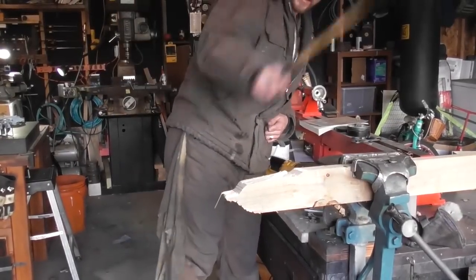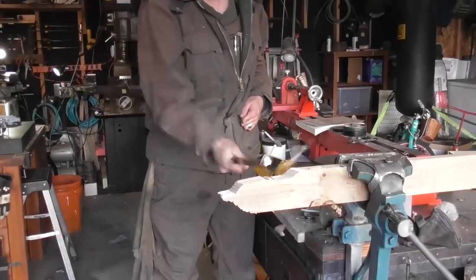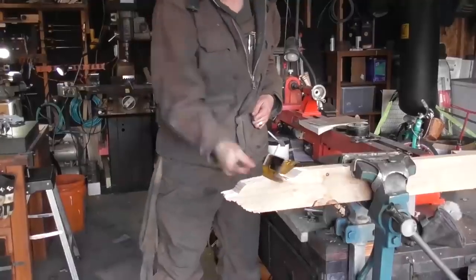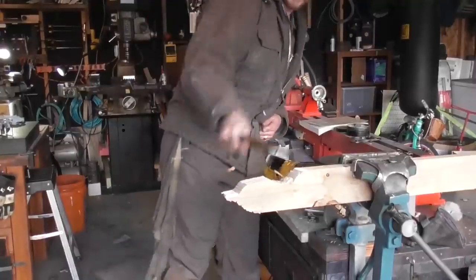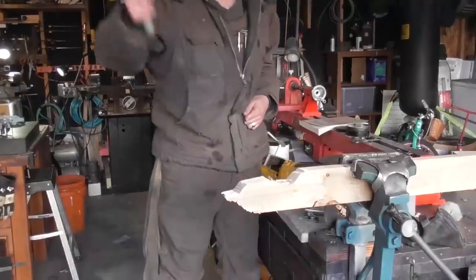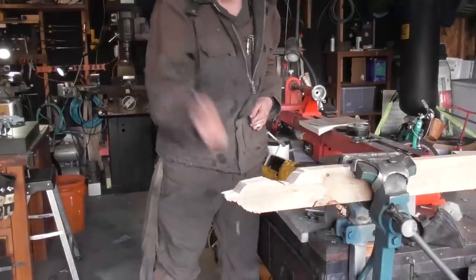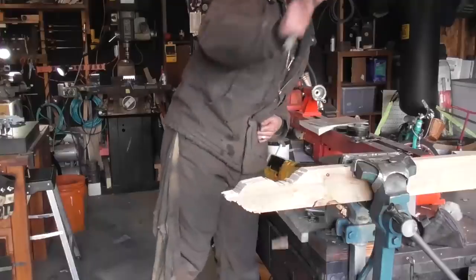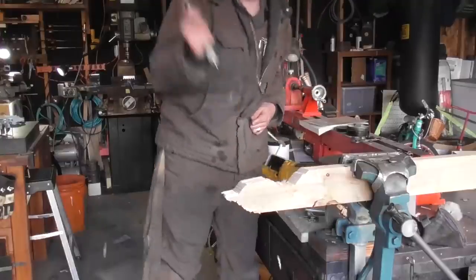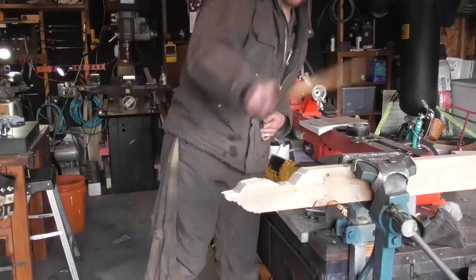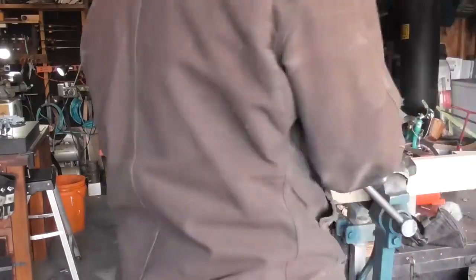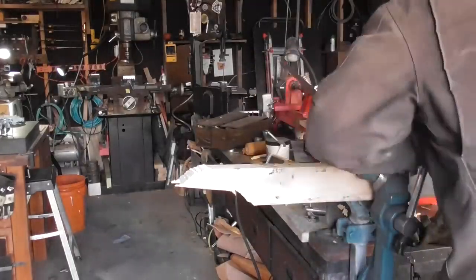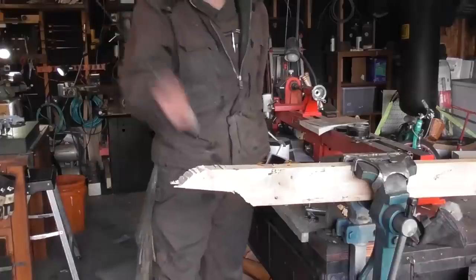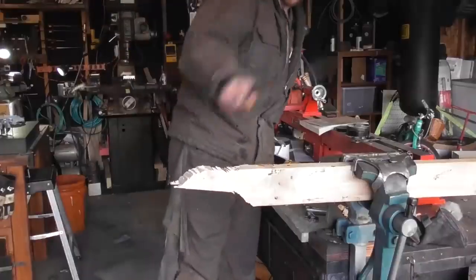I also try, for the sake of testing, to really make sure that it's held up, especially on a blade this long, to actually just focus on one area when you're chopping. Because you could vary it up, chop at different parts of the blade, and it's going to do less damage to the edge overall. So if you focus on just one area, then you really make sure that that area is getting the brunt of the chopping, and that part of the edge is going to be having the most stress put on it to make sure that it can hold up. So anytime there's testing like this, you want to make sure that you're really just focusing on one area to see that it holds up.